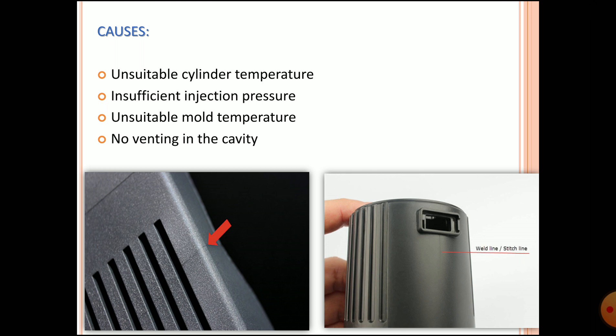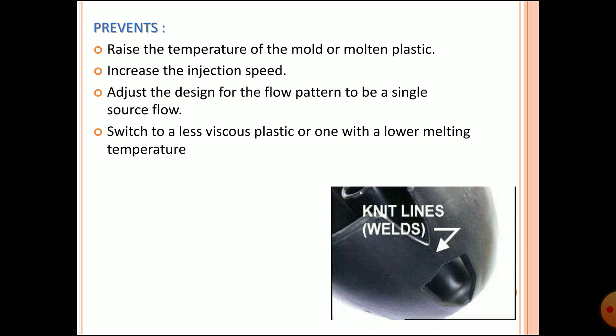Why do these occur? Causes include unsuitable cylinder temperature, insufficient injection pressure, unsuitable mold temperature, and no venting in the cavity. Prevention: raise the temperature of the mold or molten plastic, increase the injection speed, adjust the design of the flow pattern to be single-source flow, and switch to a less viscous plastic or one with a lower melting temperature.